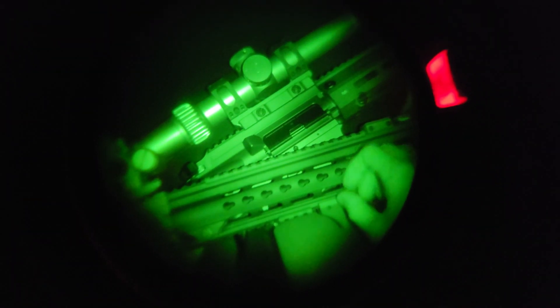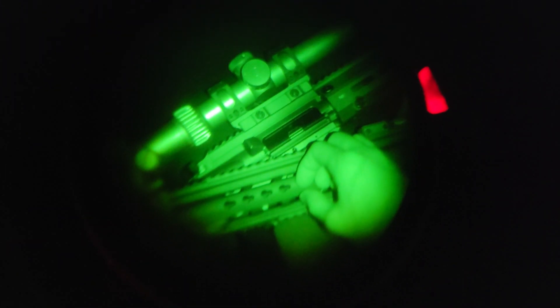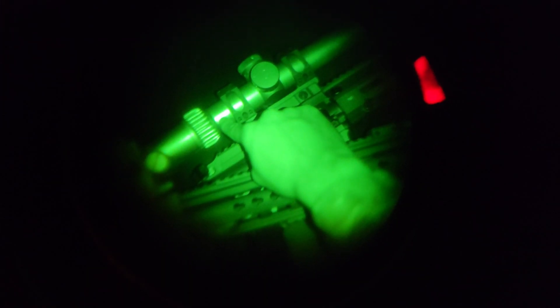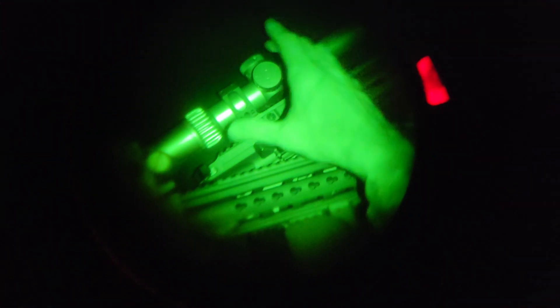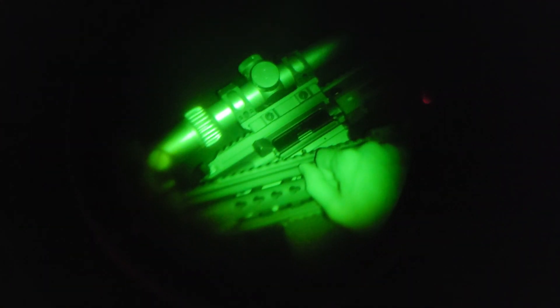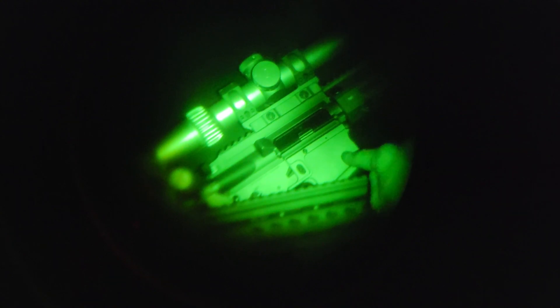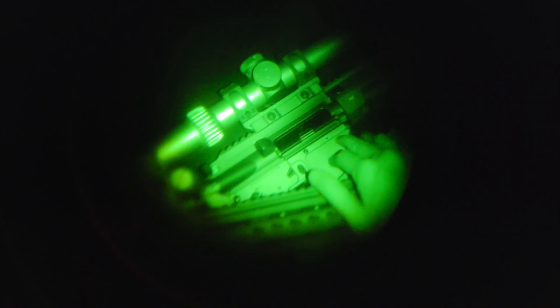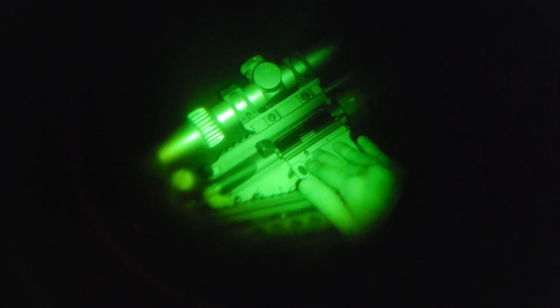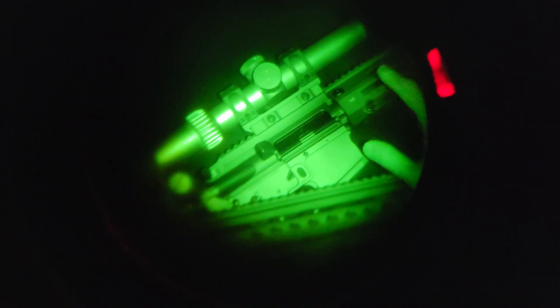This is not the case with most anodization — that was the other thing. Branching out into general gun finishes, for the most part you do want to avoid anodization if you want good NIR camouflage. For example, the Schmidt & Bender short dot up here — just anodized aluminum body — that thing is just glinting and reflecting a lot of light. Going back to that regular anodized ADM4 lower, you can see that also really shines way differently than everything else.